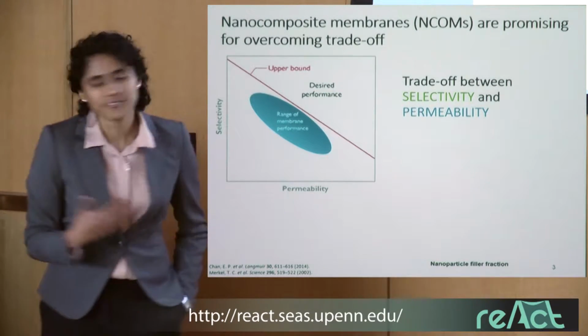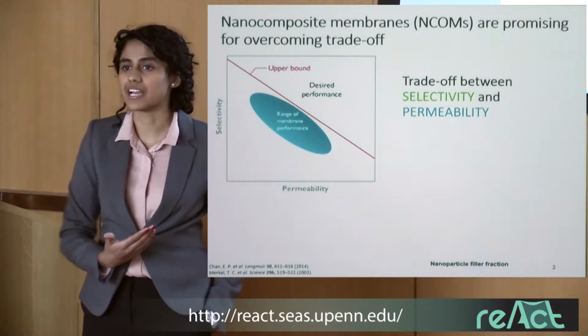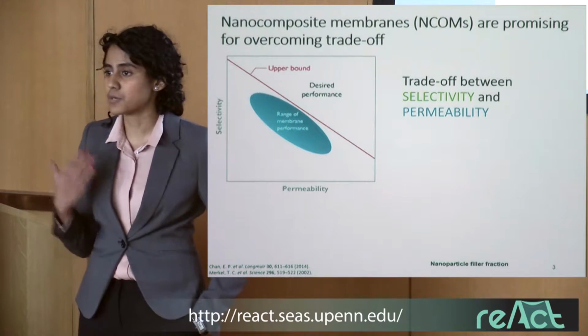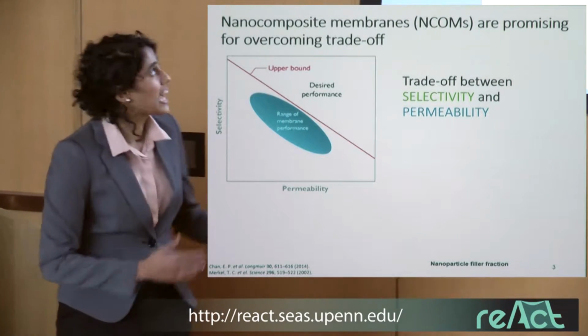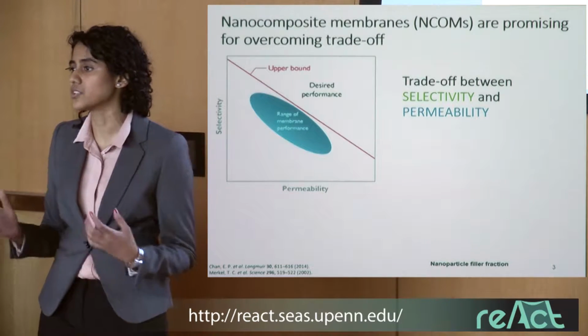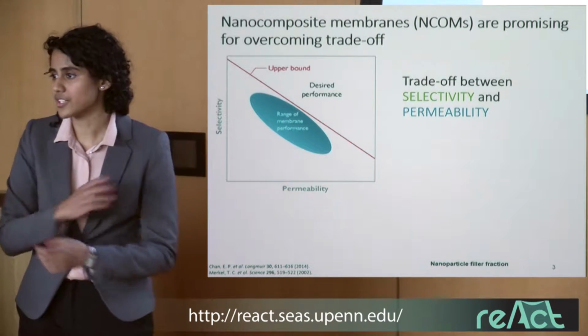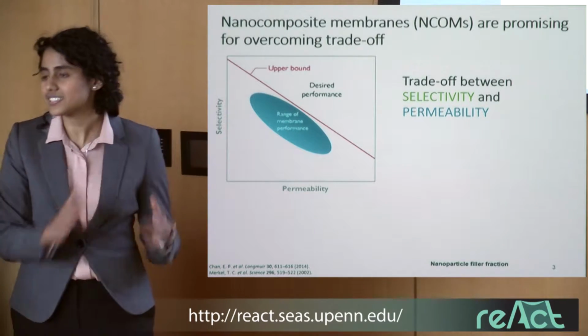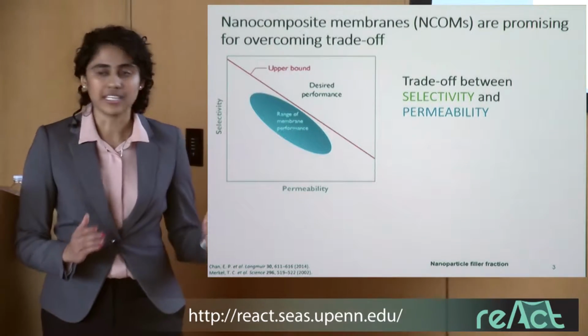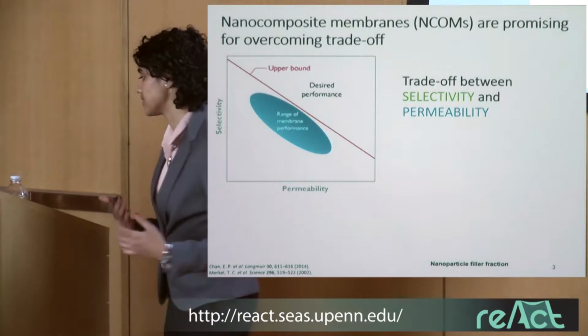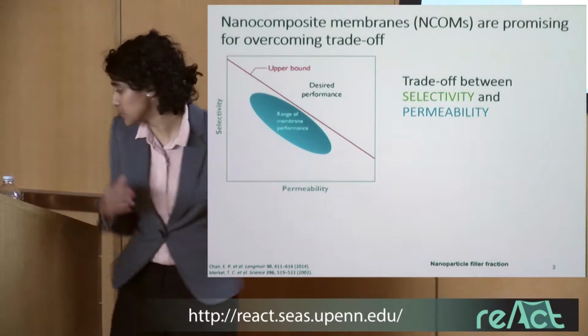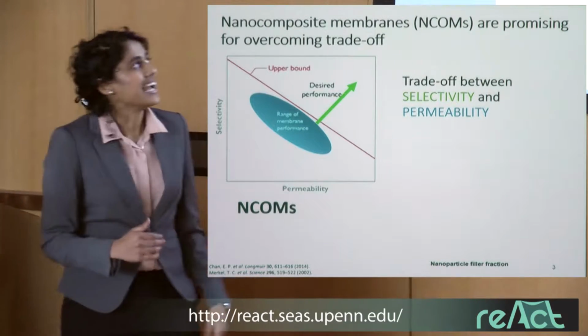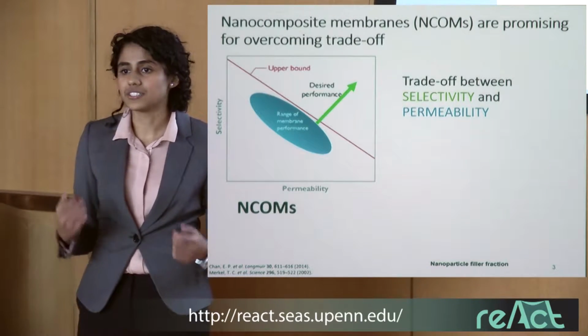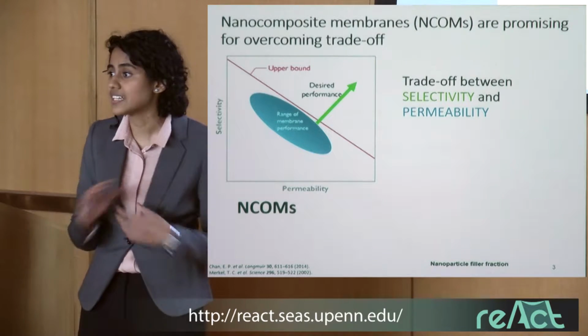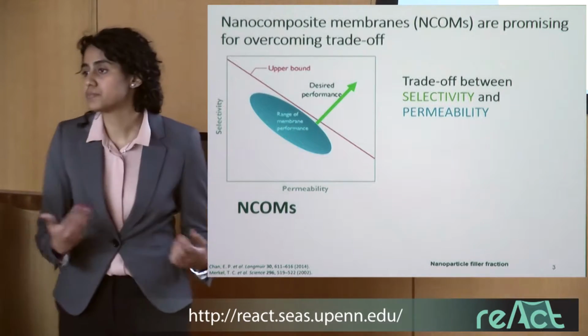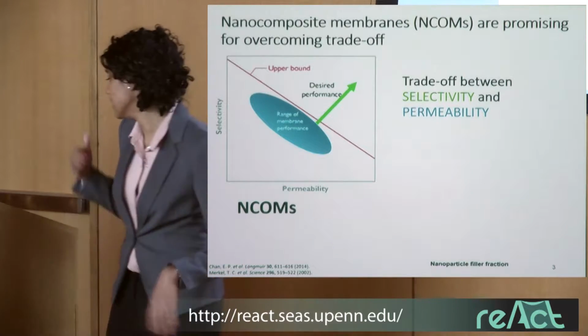So really quickly, conventional membrane technology has this drawback, this trade-off between permeability and selectivity. So basically, as you increase the purity of a permeate going through a membrane, you get less throughput, or you get less flow through it. So there tends to be this conventional upper bound in both gas separations and water purification that we would really like to drive up. And previous studies have shown that incorporating nanocomposites into the selective layer of a membrane can really drive up this permselectivity of your membrane.